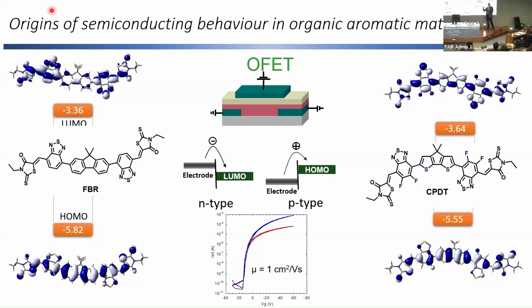And from a charge injection perspective, we're interested in, if this is an electron device, if it's an N-type semiconductor, the gap between the electrode work function and the semiconductor LUMO. We want to minimize that gap in order to be able to inject charge. This is an exothermic arrangement, a hetero arrangement here. The electrons will fall down in energy, so this is favorable. In this case, we also have a favorable arrangement for holes. So you want the electrode to be slightly deeper than the HOMO energy. If it's too deep, it becomes very leaky. So you want to be able to manage these.